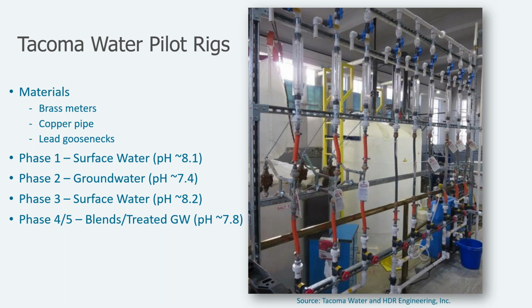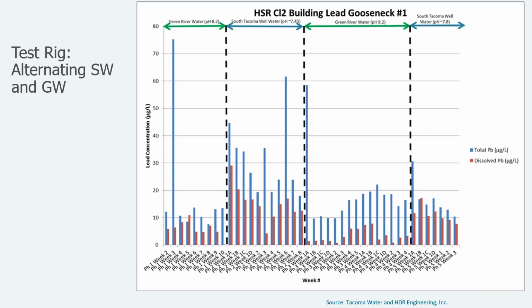And then the whole rig was converted over to groundwater at pH around 7.4, and another set of materials were harvested and analyzed to see the degree to which these changes were occurring. Of course, simultaneously, we were doing sampling off of the rigs to see what the lead levels were. These graphs show in blue is total lead, red is soluble or dissolved lead, so the difference between them is